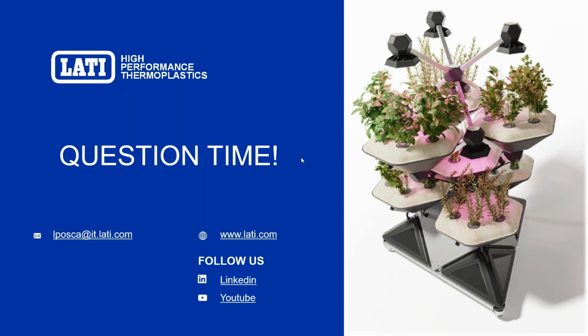Fourth question, how abrasive are the graphite or the ceramic particles on the tooling? Very good question. Many of the ceramic particles can be abrasive. Of course, if you already have experience with glass or carbon fibers, you know what I'm talking about. Graphite normally is not very abrasive. It's a rather soft filler, so graphite is normally not a problem. Ceramics can be more of a problem, especially if you mix ceramics with flame retardants and glass. We have some glass fiber filled flame retardant thermally conductive plastics which require hardened steel with surface hardening like titanium nitride or stellite, PVD deposition. Graphite is normally not a problem. Ceramics can be something to be properly managed.